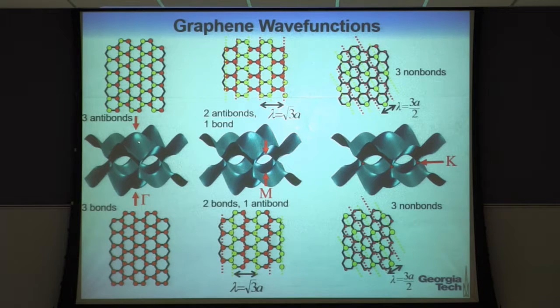So if I go to a different momentum, what happens is that these wave functions get multiplied by a phase factor, a complex phase factor, e to the i k dot r. And if you look at some high symmetry points like the M point, then what you'll find is that I have a wavelength that's determined by the k vector, just by de Broglie's relation, right? P is h over lambda, and h bar k is equal to P. So lambda is square root of 3 a here, and you can see that along any given wavefront here, all of these things are in phase. Whereas if I go to the higher energy side, that's up here, then I alternate in plus minus along a wavefront. Okay, so that makes this higher energy than that one, which is why you get the gap at the M point.